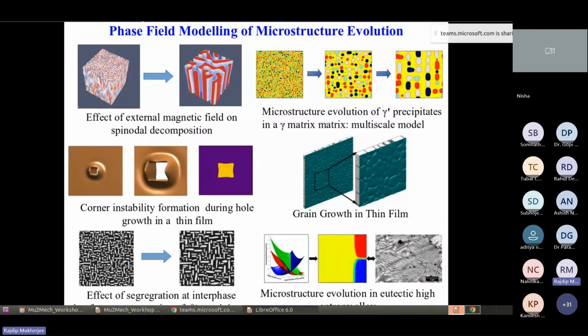So in this one, you can see that we have started the microstructure evolution during solidification, meaning you have a liquid of eutectic composition. In a phase diagram, you have a eutectic point. If you cool this composition below the eutectic point, it will solidify. Say there are A and B atoms. Like you are saying, there will be A-rich and B-rich phases; it will decompose and form a lamellar kind of microstructure.